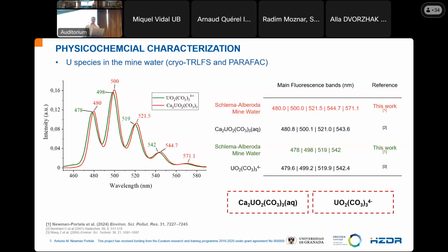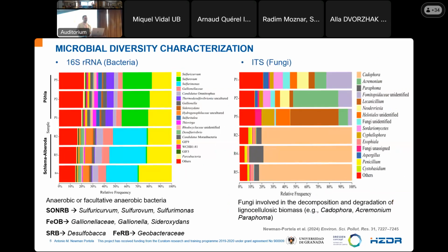By TRLFS and PARAFAC analysis, we identified two different species in the Schlema-Alberoda mine water. First, the calcium uranyl carbonate species, as we predicted before by the chemical speciation code, and uranyl carbonate. Both species are presented here in the red and green lines, and you can observe how the fluorescence bands match with the reference.